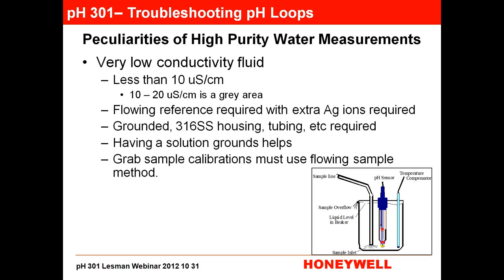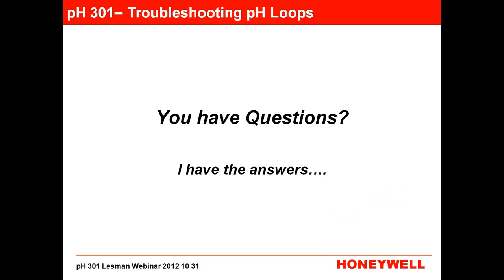And then you know that all the contamination is in about the top quarter to the top third, whereas you're getting a real reading at the bottom. So then you get a good grab sample that way, and then you can make your adjustment on your live reading. So you have to have a flowing sample for that.